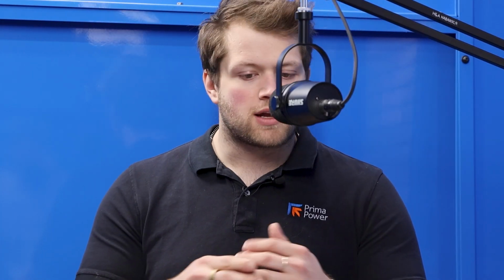When we start talking about pulse mode, you start talking a little bit more about different parameters. So how long it's on for. You have to command a certain amount of time that it's pulsing for. How many times per second are you pulsing? We'll run it 200 times per second. Turning on, turning off, turning on, turning off. And then, of course, your peak power. So you're turning it on, how high do you go?